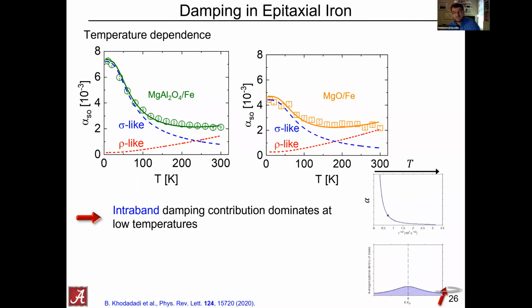But again, this would be what you refer to as the bulk, because we are talking about 25 nanometers. So it would be very difficult to say anything about interfacial contributions here. I would have to look at the paper. It can be very difficult to actually disentangle interfacial contributions to the damping from the two magnon scattering contribution. So that's another complication you struggle with. Does that somewhat answer your question?